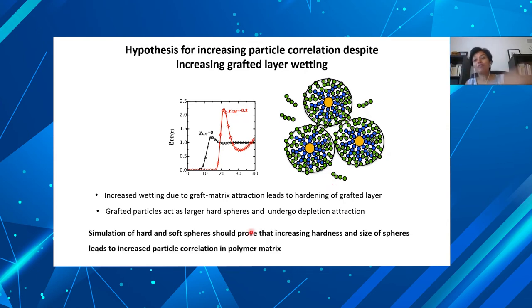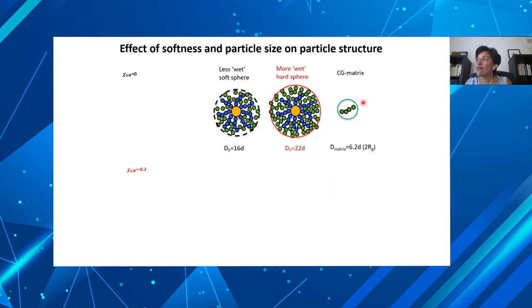So here we went even more coarse-grained, right? Where each bead is not a polymer, but the whole polymer is represented with some spheres. And so now we have the whole polymer matrix as a sphere, coarse-grained. The whole grafted particle is also one sphere. But the way we model these spheres is to reflect what we just want to test, which is less wet, so small and soft, more wet, large and hard in a matrix.